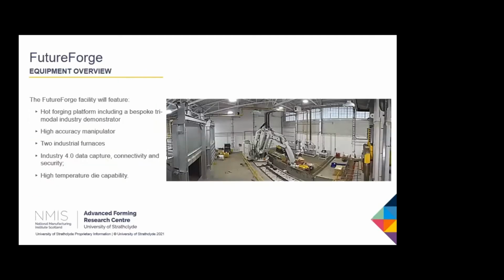So, just to give you a bit of an overview again of what's happening. The FutureForge facility will feature a hot forging platform, including bespoke trimodal industry demonstrators, a high accuracy manipulator, two industrial size furnaces, Industry 4.0 data capture, connectivity and security. We've also thought about all the security issues and the like. And the other important point to note is that particularly for the closed die and the open die, we'll have high temperature die capability. So we can go up to about 600 degrees C for both the closed die and the open die facility process if need be.